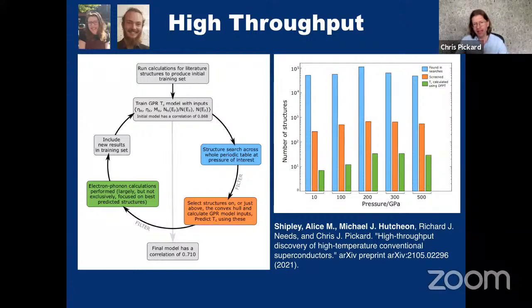So how did the calculation progress? Well, we did these sweeps for 500, 300, 200, 100, 10 GPa. And I might end up with approaching 100,000 structures for each of those pressures. But we can't calculate the TC for 100,000 structures. So Alice screened these structures and told us the ones that most likely might be superconducting. And then those ones, Michael went off and calculated using Quantum Espresso and density functional perturbation theory. And that's tens of structures for each pressure. So we ended up in total doing about 100 TC calculations.